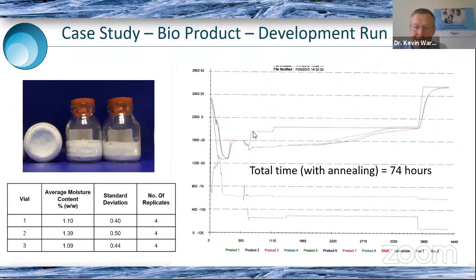We found that even by having a shelf temperature of -15 going up to -10, we could still maintain the product below its critical temperature until the product temperature started to rise, indicating that it was dry. So here now we've already halved the original drying time. So we've gone from 149 hours to 74. We've still got quite a low moisture content with good standard deviation, and the product looks fine, although there's maybe a small amount of foaming around the top here.